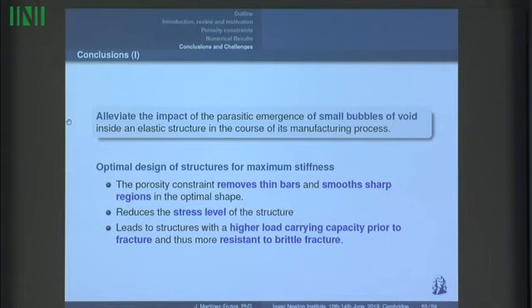Also, with respect to the optimal design of the structure, what this formulation does is remove thin bars and smooth sharp regions of the shape. As a side effect, it also reduces the stress level and provides a higher load carrying capacity prior to fracture. So the designs are not optimal for fracture, but have a better behavior against fracture.